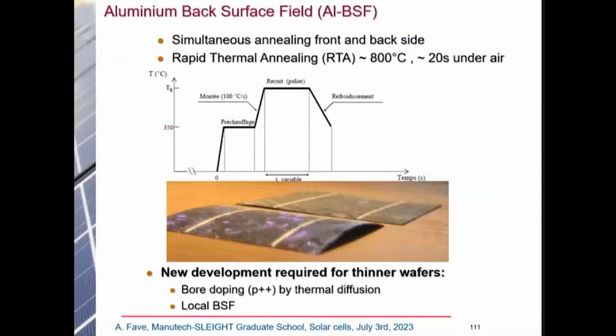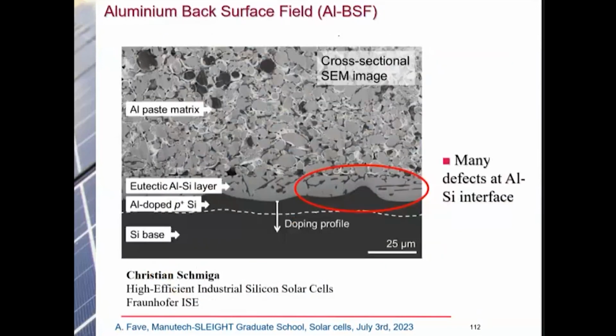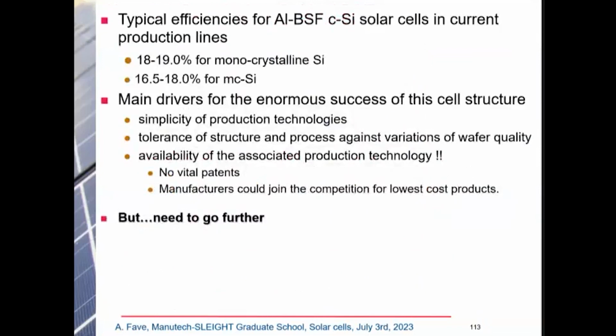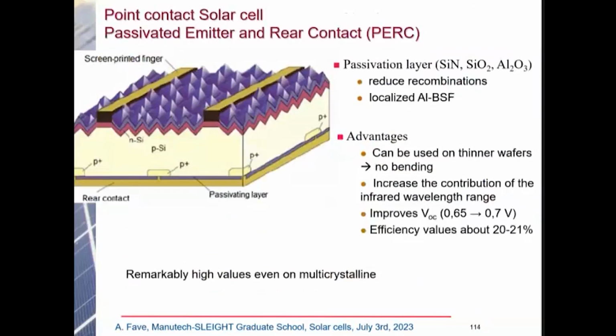So that's a problem. Another problem is that at the interface between silicon and aluminum, at the surface, you have many defects that will bring other recombinations of electrons. Okay. So it's a nice technology. We can reach almost 20% with this, 18–19%, but we cannot increase the efficiencies more.